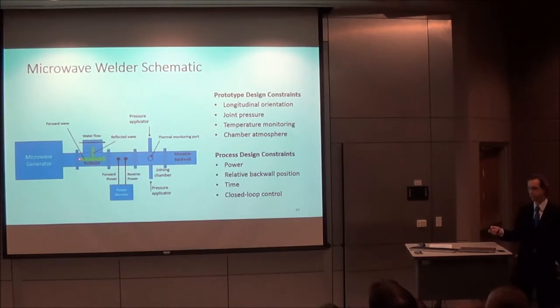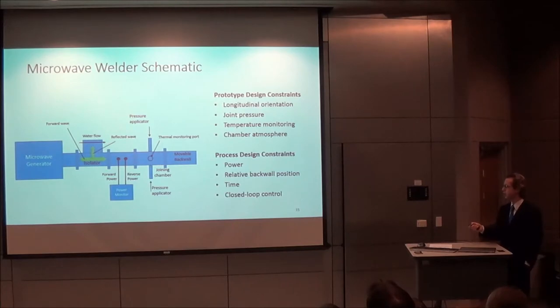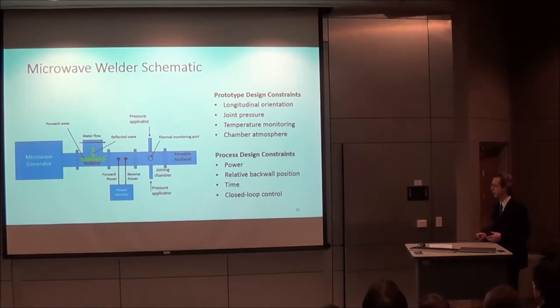And then we have the power meters, which measure forward and reflected power. The joining chamber, or in a different prototype, a chamber used to heat different materials, and a movable back wall. And so the joining chamber utilizes the longitudinal direction that will be shown to be preferred, as well as incorporation of joint pressure and monitoring of the temperature of the target, and then changing the chamber atmosphere, purging it or pulling out the air or increasing the pressure inside. All of these things were important to incorporate in this joining chamber.